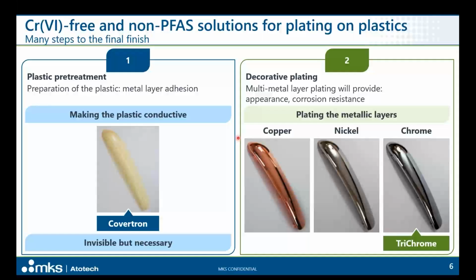And for decorative plating, doesn't matter if it is plating on plastic or on different substrates, normally a multi-metal system is used in the industry. Copper, nickel, chrome are being used. And of course, chromium 6 is used for the plating of chromium as the final finishing layer. And our trichrome family is a direct replacement of this chromium 6 plating applications.